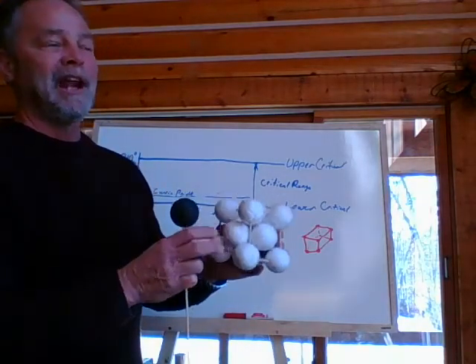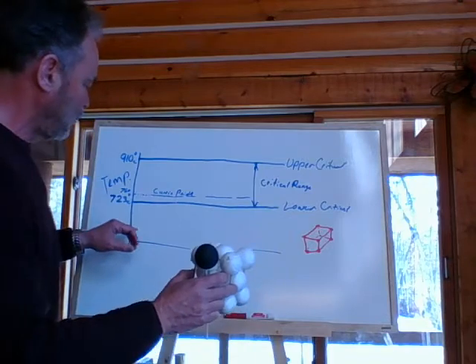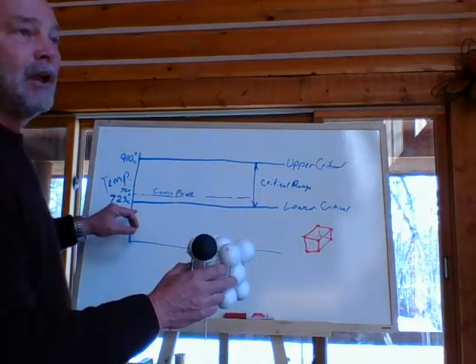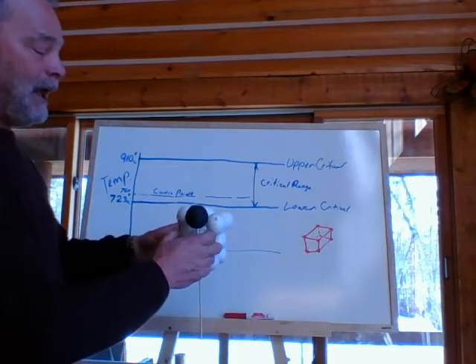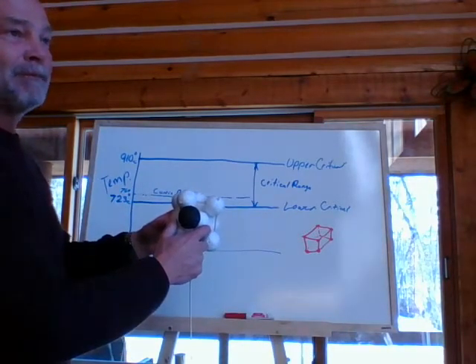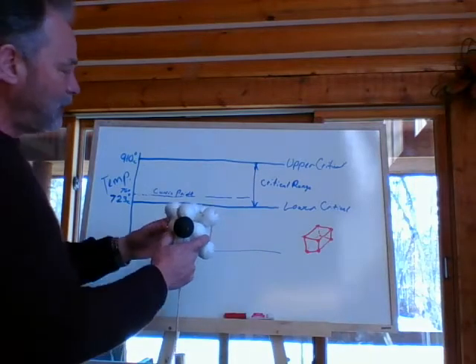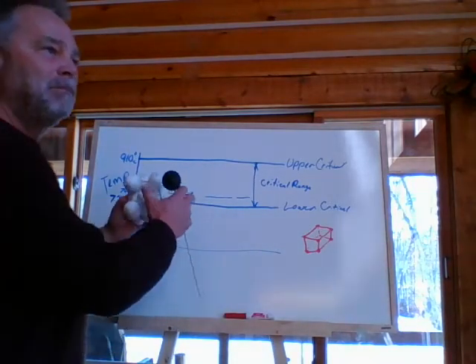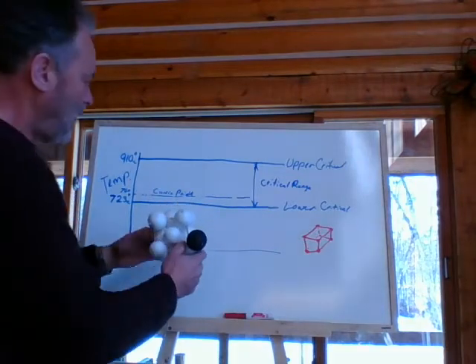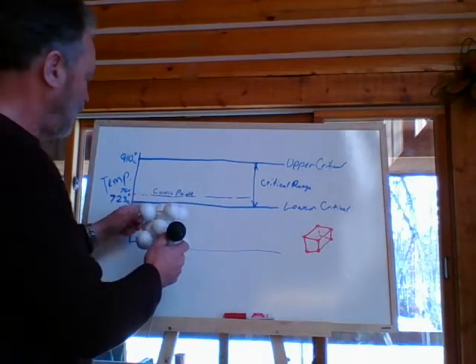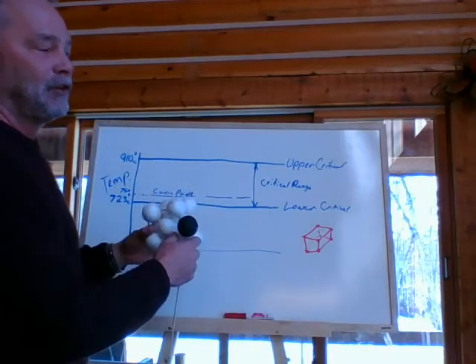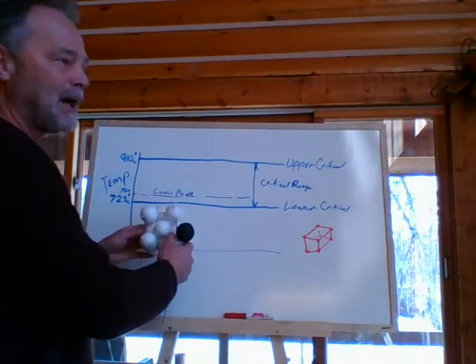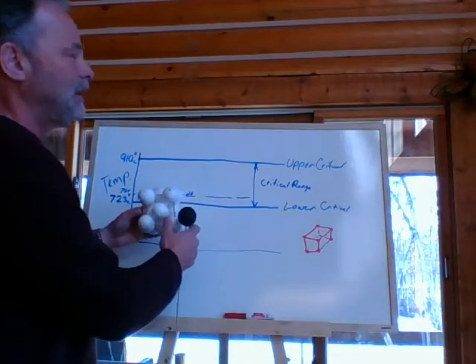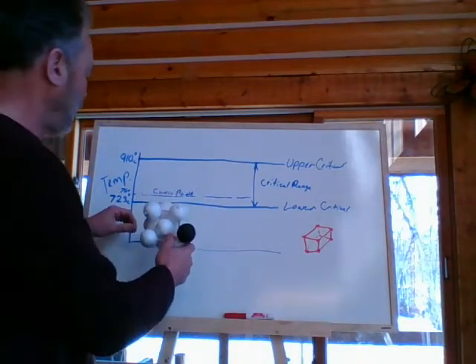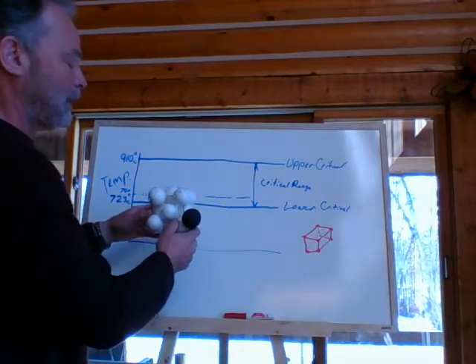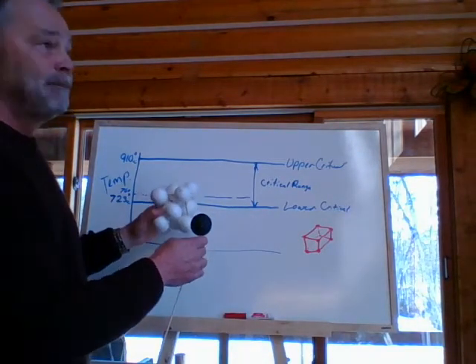What we do is we put energy in, and that's called tempering. So we'll heat it up to a range of 3, 4, 500 degrees. And it's below the lower critical. That allows some of the carbon to escape. And we cool it slowly. So it takes a little bit of the hardness away, but it makes the steel tougher. The higher the temperature that you raise it, the more carbon escapes and the softer it gets. So it becomes perhaps tougher, but it's losing the hardness, and it's losing more hardness as you get warmer and warmer below the lower critical. Interesting enough. And that's how that works.